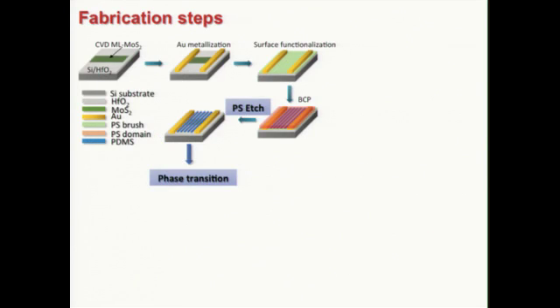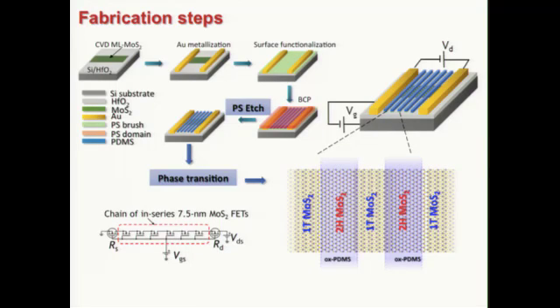This is the summary of the process flow. We start with depositing CVD monolayer molybdenum disulfide, or few layer molybdenum disulfide, on a silicon substrate. We put down the metal contacts. We have to functionalize the surface to improve the adhesion of Block-Copolymer to the surface. We deposit and develop Block-Copolymer, and finally we etch the polystyrene line. So we are left with this parallel PDMS line on MoS2. And finally we apply the phase transition that I already explained.